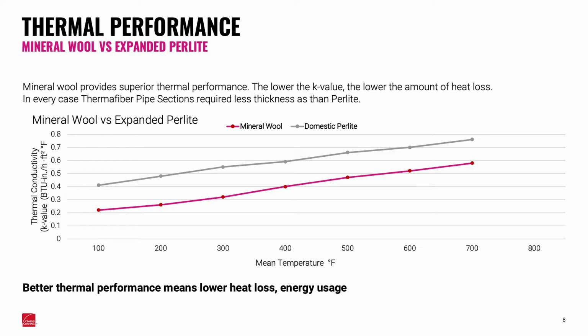So to start off with, because this is insulation, we're concerned with how it's going to perform as far as resisting heat flow, going from a hot side process temperature piece of equipment to regular ambient conditions. So what we want to look at is the thermal conductivity, and essentially the lower the line, the less heat loss through a material in a given period of time. So in other words, the lower the line, the better the performance. Now, just looking at numbers, if you look over on the far left-hand side, you can see at 100 degrees, the K value is 0.2 for mineral wool, just a little bit above it. And you see for expanded perlite, it's slightly above 0.4.